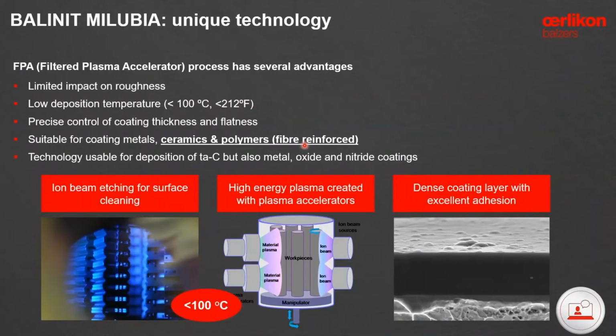We call it the filtered plasma accelerator process, FPA. As you can see in the diagram below, we have ion beam sources with a filtering process to eliminate the droplets that reach the workpiece. So it has a very limited impact on roughness, a very low deposition temperature, under 100 C or under 212 Fahrenheit, and very precise control of thickness and flatness and uniformity.